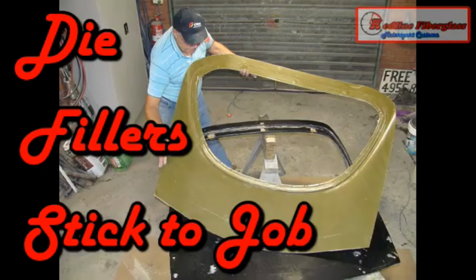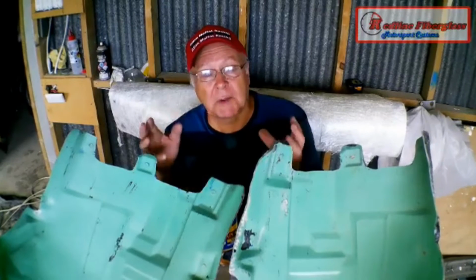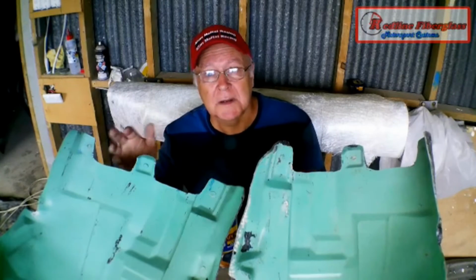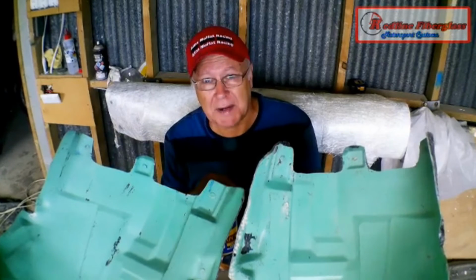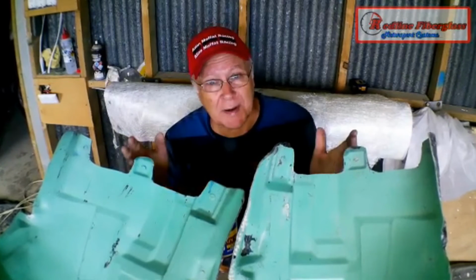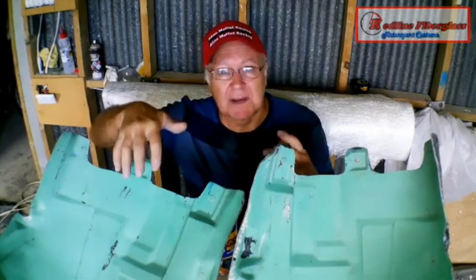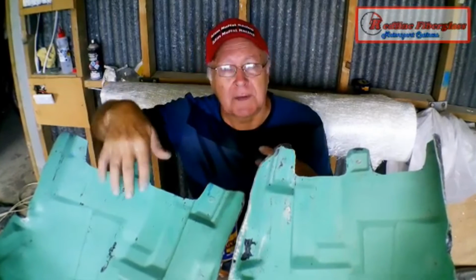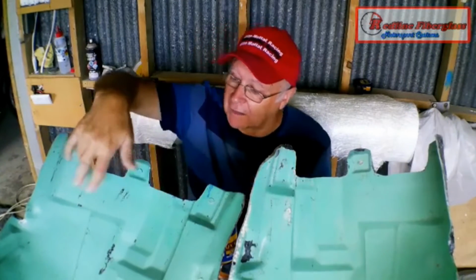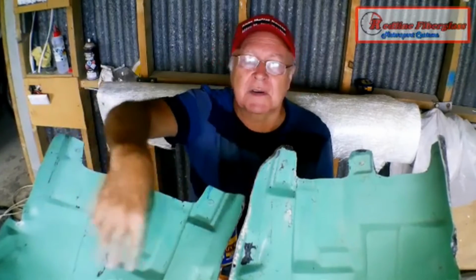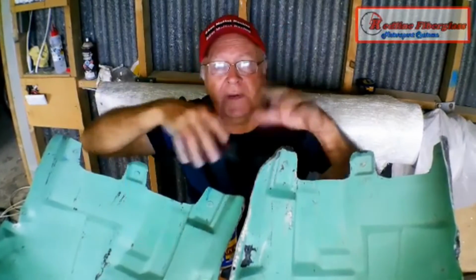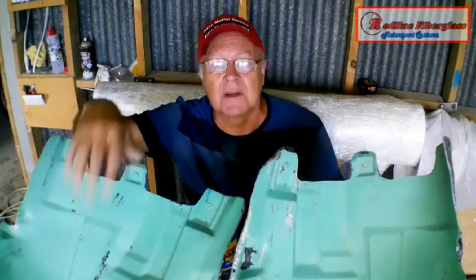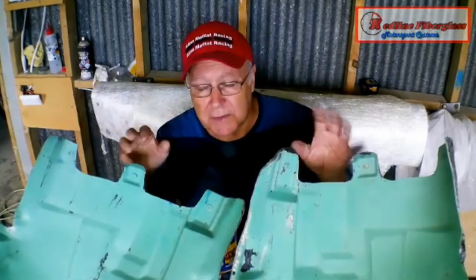You've sculpted your die plug. You fiberglassed over the top of it to make a mould, but when you try to separate the two, your fillers stick to the fiberglass, and you've got to go around and clean off all the plaster and car body filler that you've used to fill in the little imperfections. Nightmare job. The reason that's happening is because you haven't sealed your die plug properly.